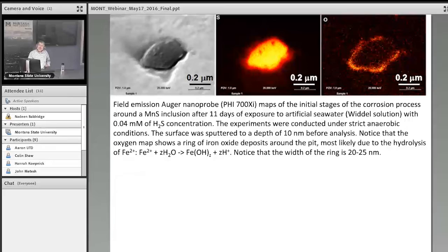And then this was sputtered about 10 nanometers to remove all the surface oxide. And we see a ring of oxygen around this manganese sulfide, at the interface between the iron and manganese sulfide. And that was a key. This is so important information. You cannot get this information with EDX. This is about 25 nanometers wide here.